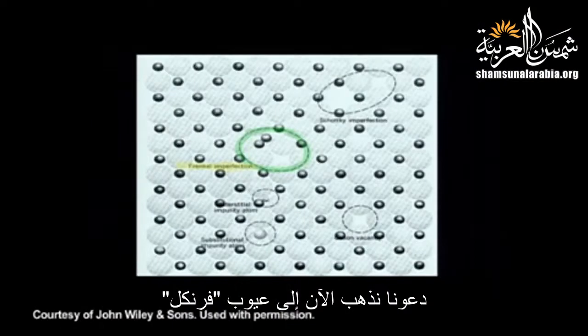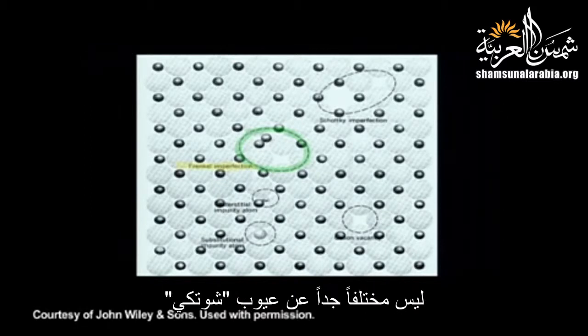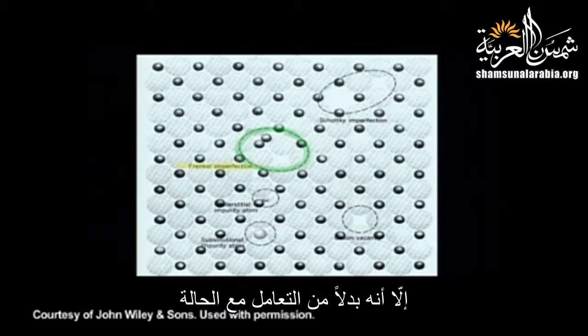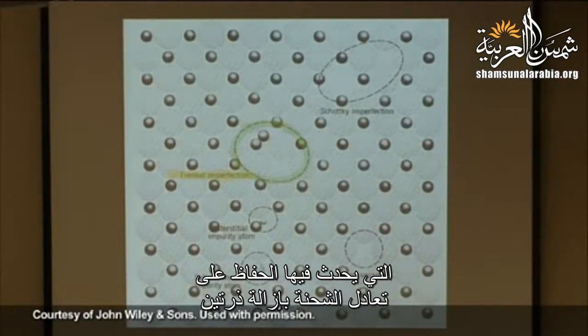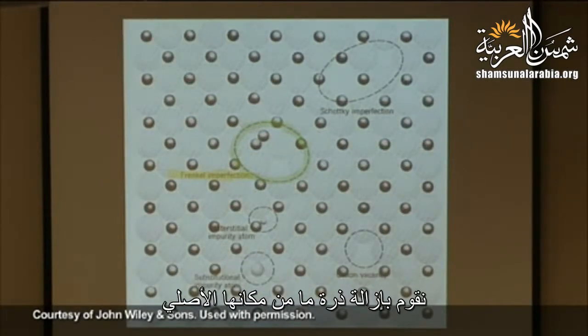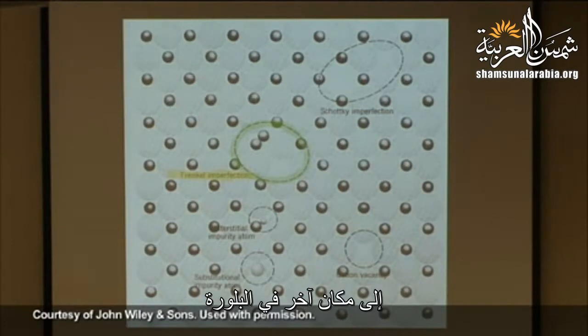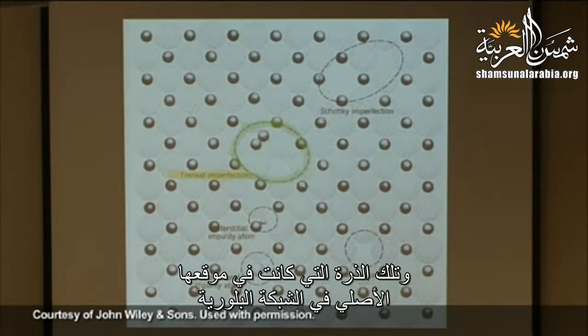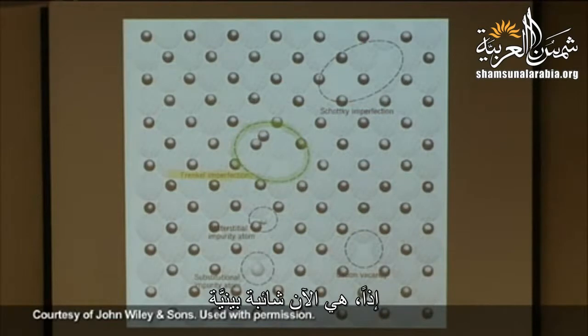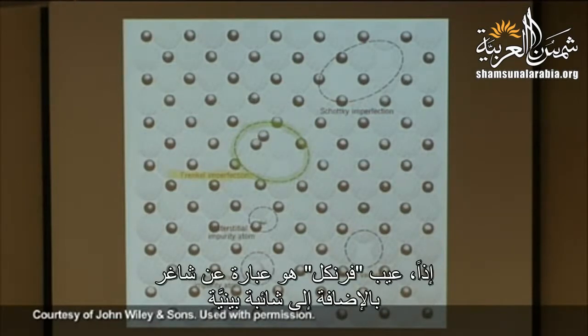Okay. So let's move on to Frenkel defects. In the case of Frenkel defects, it's really not so different from Schottky defects in some sense, except now, instead of dealing with a situation where we maintain charge neutrality by removing 2 atoms, we actually displace 1 atom from its initial location to a different part of the crystal. So we're creating a vacancy right there, and this atom, which was originally sitting on a lattice site, is now displaced to an interstitial location, so that's an interstitial. So a Frenkel defect is a vacancy and an interstitial.